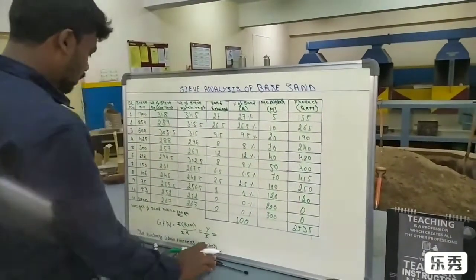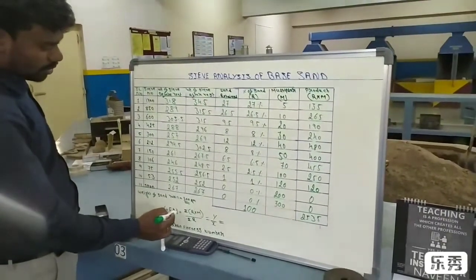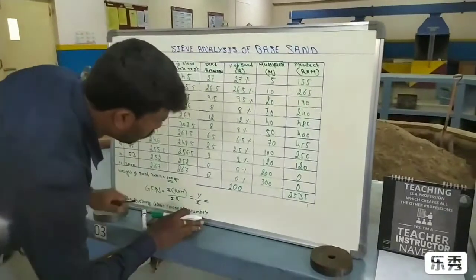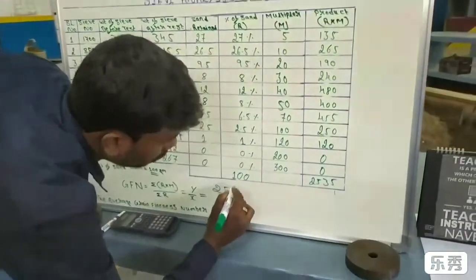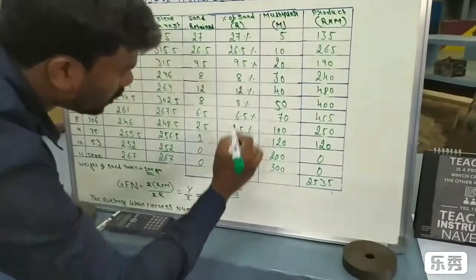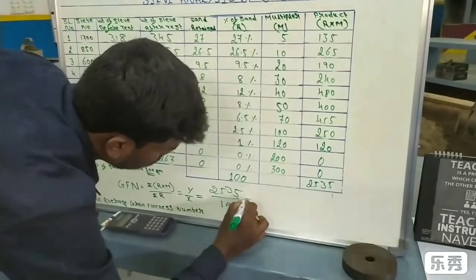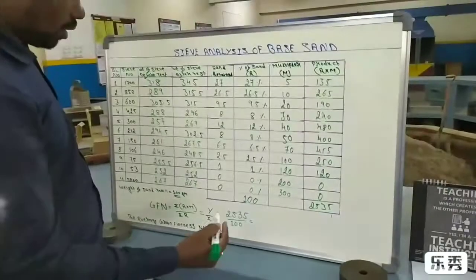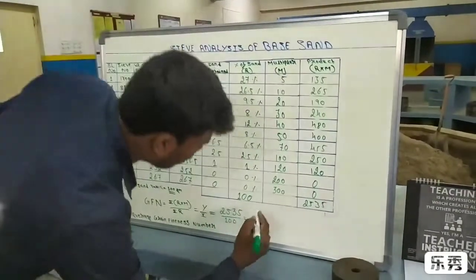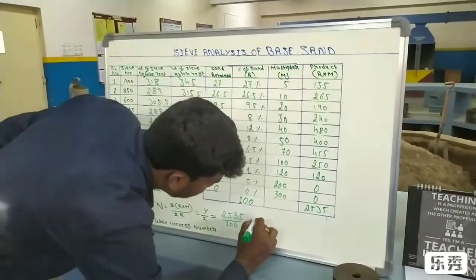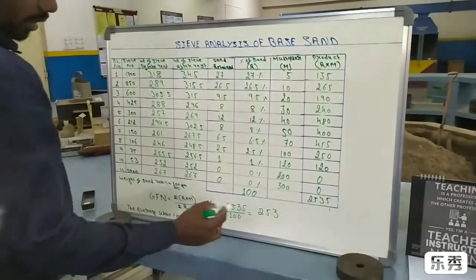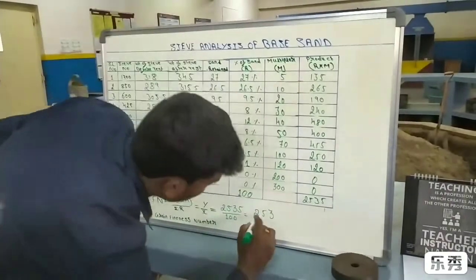Now we find the GFN — the grain fineness number of the sand. We calculate it by dividing the total product by the total percentage of sand. The result comes to 25.3. The grain fineness number of the base sand is 25.3.